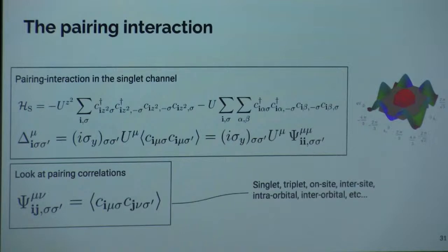Now we would like to study superconductivity. And to do this, we assumed the simplest type of pairing we could. So we started with a pairing interaction in the singlet channel, so a singlet on-site intra-orbital pairing only. There's a good reason for that. If you look at the orbital content available at opposite momenta, you see that if you have a red at one k, you also will have red at opposite k. So interorbital pairing is rather unlikely in this system.